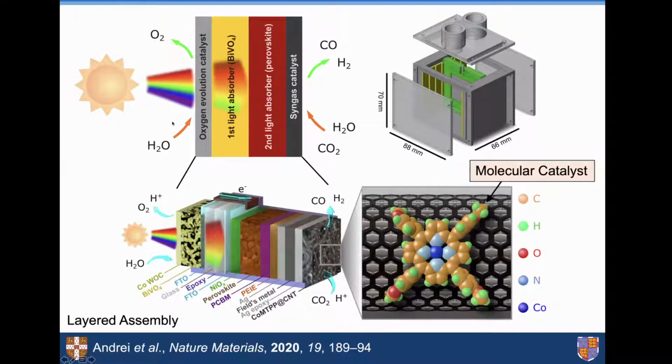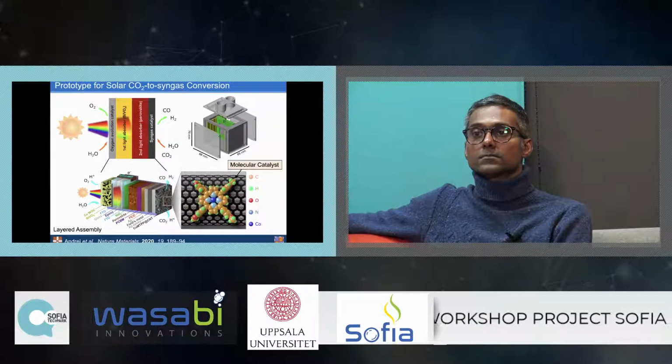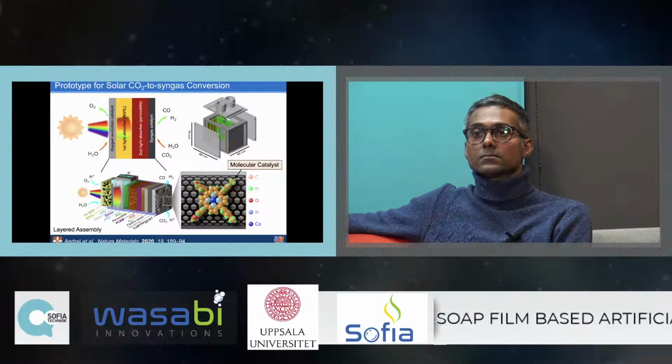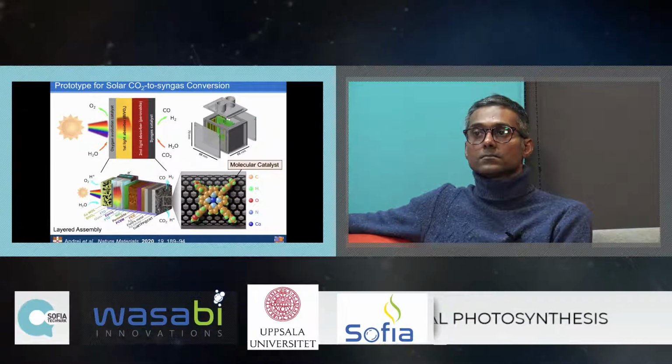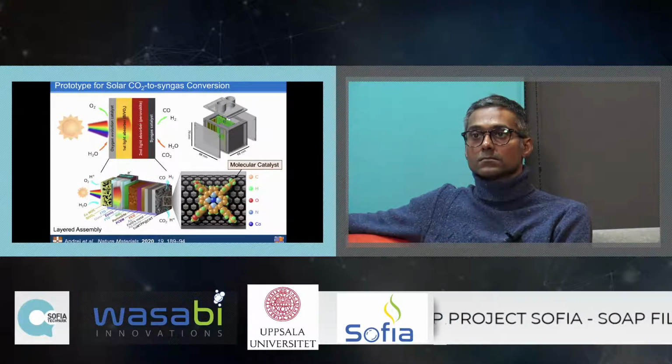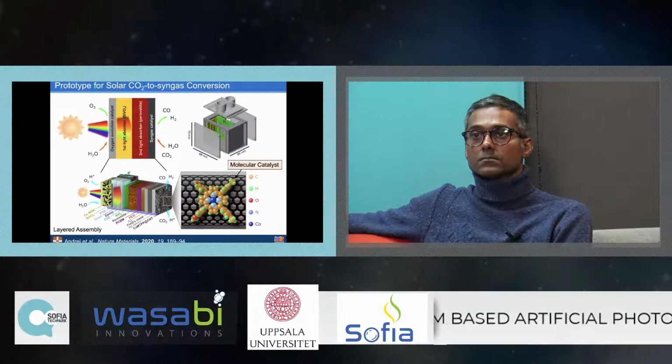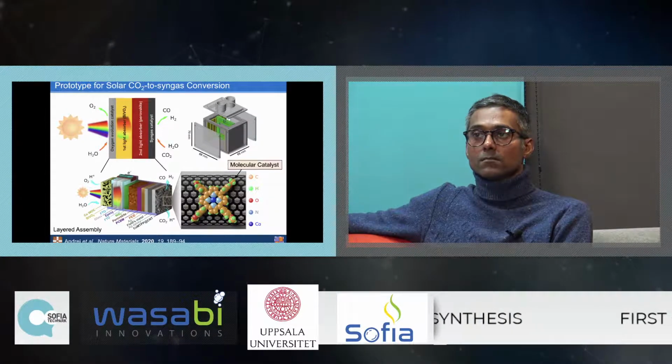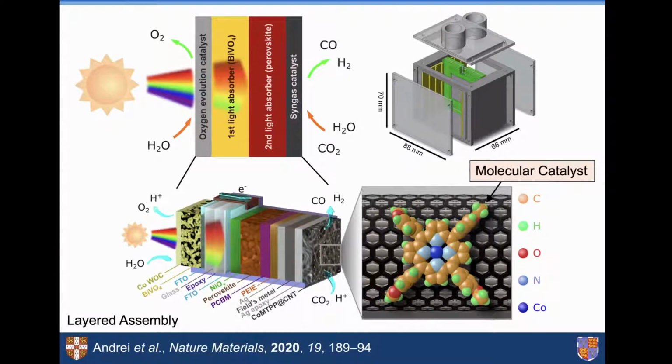The simplified scheme here does not really do justice to the layered design that was necessary to make this work. I will not discuss it in any detail, but you should see it requires a combination of many different layers and materials, and they all need to be tuned and optimized to operate with the best possible performance. One example would be that these lead halide perovskites are arguably the worst possible material to use in such a device because they're extremely moisture sensitive. So you really need to encapsulate them so that they do not degrade very quickly. And we've managed to do this quite well.